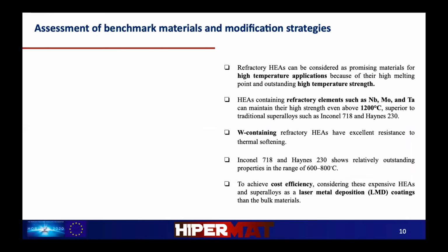This was all about the high entropy alloy and superalloys. Here is the assessment of benchmark materials and modification strategies for Hypermat. The refractory high entropy alloys can be considered as promising materials for high temperature applications because of their outstanding high temperature properties. Addition of niobium, molybdenum, and tantalum can maintain high strength even at 1200 degrees Celsius, which is superior to traditional superalloys such as Inconel and Haynes 230. Also, modification strategies can include tungsten addition, which can show excellent resistance to thermal softening.